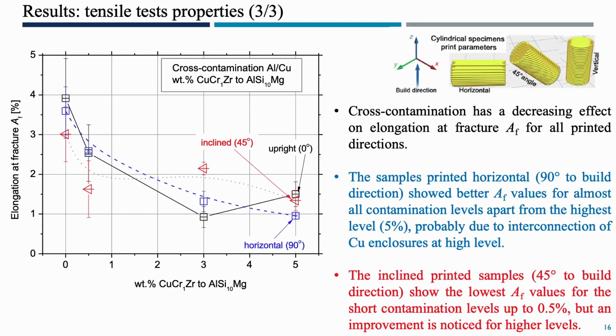Of course, you have some variances with the horizontal print job or with the one inclined at 45 degrees. Actually, you have a decrease for the red symbols. You have an almost linear decrease, except for the low contamination level. Of course, we possibly have to repeat some tensile tests.